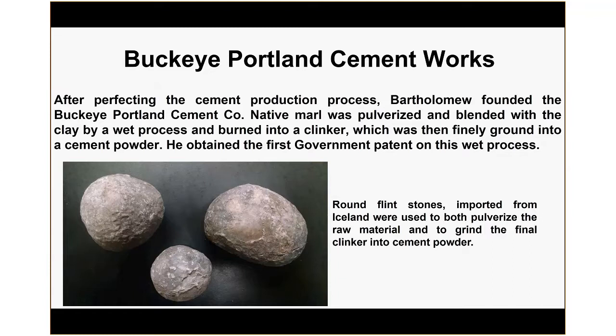Now you can see in this picture here, when we have a big roller mill, nowadays we charge them with very large steel shot. Well, back then they used flint stones, and these were actually imported from Iceland, and these stones roll around with the clinker, the raw Portland cement clinker, and they grind it down into a Portland cement, a gray powder, which we know as Portland cement, which we add water and aggregate to, and we make concrete.